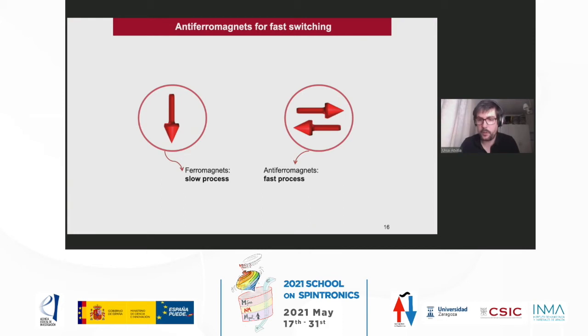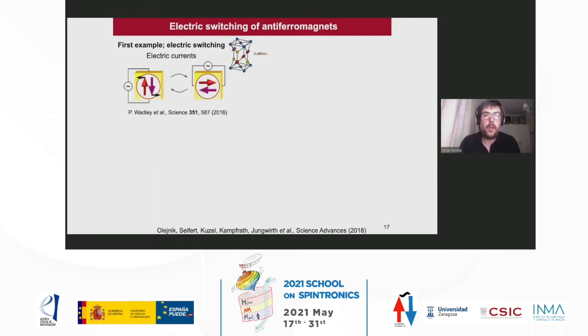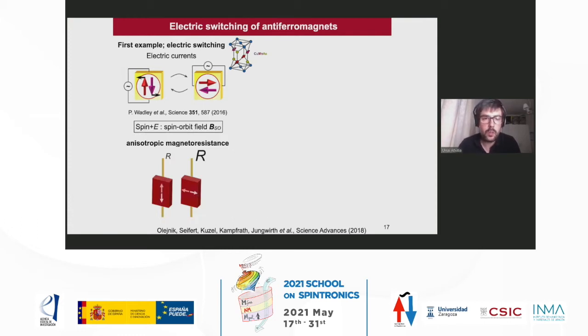So the idea now is to use electric fields instead of B fields, because electric switching of an antiferromagnet has already been demonstrated in copper manganese arsenide, part of the topic of antiferromagnetic spintronics during this school. The spin couples to the spin-orbit fields created by electric currents and switches the magnetization by 90 degrees. You can measure this switching by looking at the anisotropic magnetoresistance: when the order parameter of the antiferromagnet is perpendicular to the electric current, the resistance is higher.